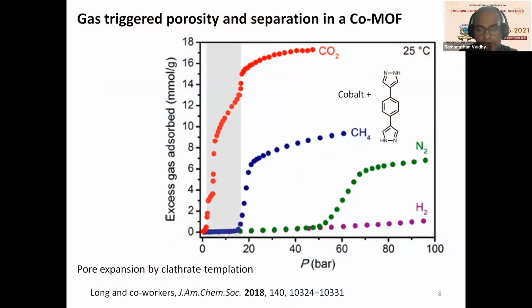Okay, so this slide is slowly getting into that. So here, this is a very nice work from Jeffrey Long and co-workers, and this was published in JACS. So what they did is, they show how from an equilibrium adsorption isotherm of carbon dioxide, methane, and nitrogen, you can see that the MOF actually is, for example, let us look at the blue curve, which is the methane. It is absolutely non-porous to methane up to a pressure of about 18 bars, okay?